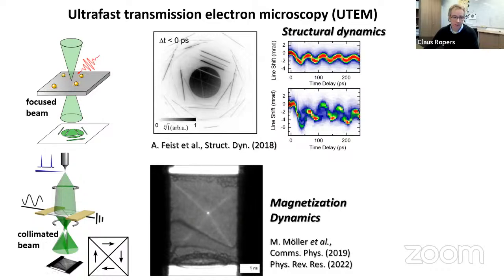we record this magnetization dynamics. The imaging condition here is actually a defocused phase contrast imaging, so you can get access in an electron microscope to the magnetization by slightly defocusing the image and using the deflection of the electron beam due to the Lorentz force in order to get contrast of the domain walls and the vortex core, which show up here as bright lines in this otherwise relatively homogeneous contrast.